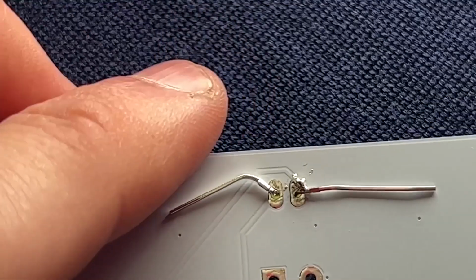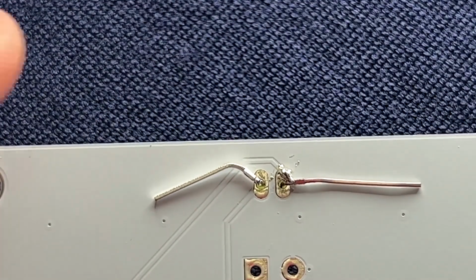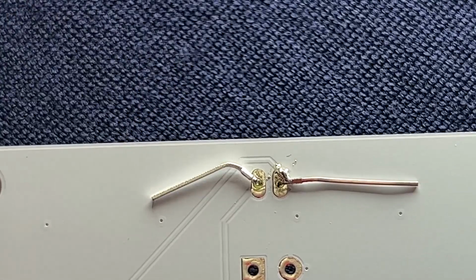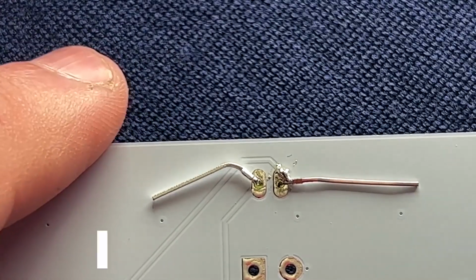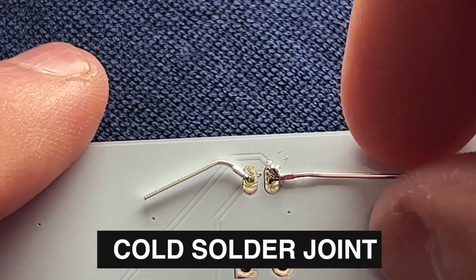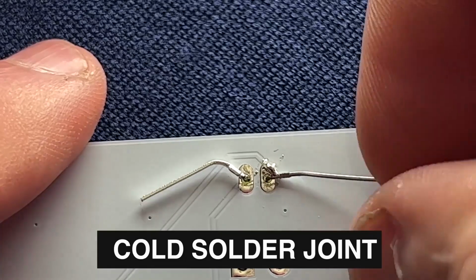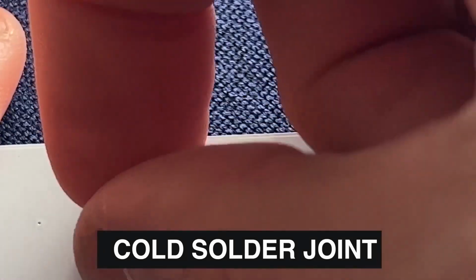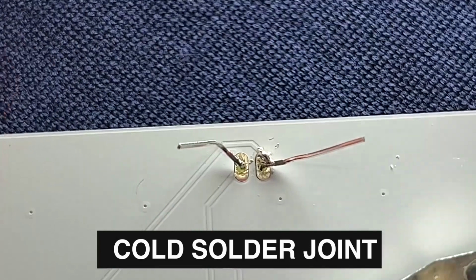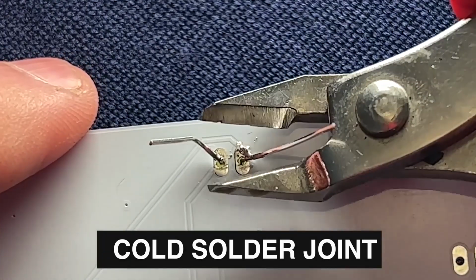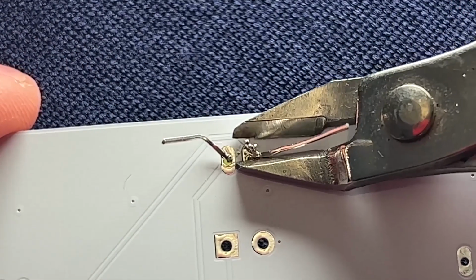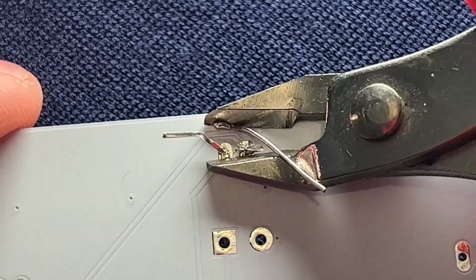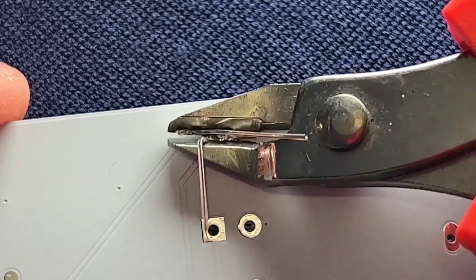Cold joints and bridge solder connections. I've done my best along the way to replicate these problems so that you can see them and see what the solution is. In this case, this is called a cold solder joint. It means the solder did not connect to both the lead and the solder pad. So watch, I'm going to trim these leads here, and what happens is the solder, because it's not connected to both the solder pad and the lead, basically has no connection any longer between the two.